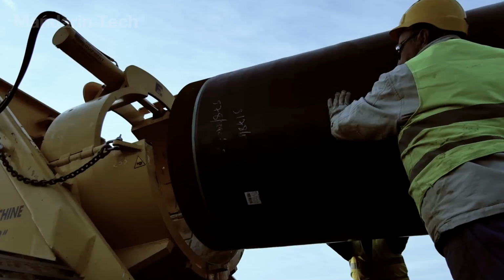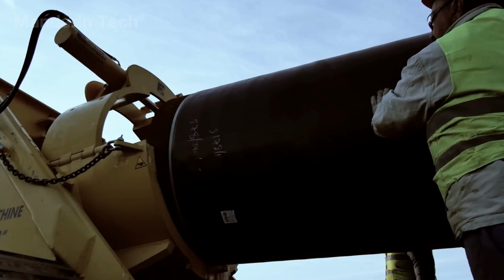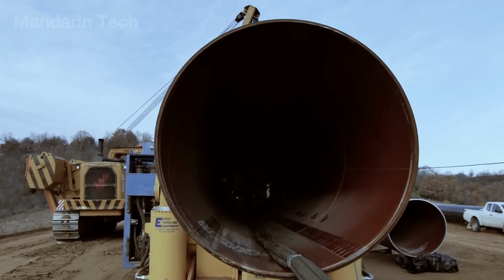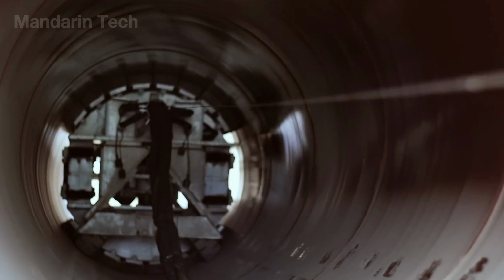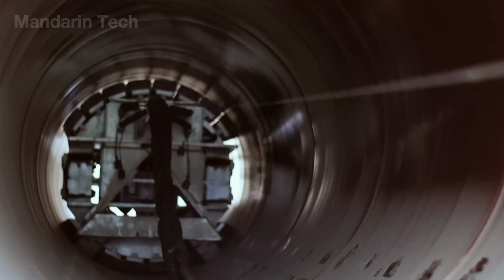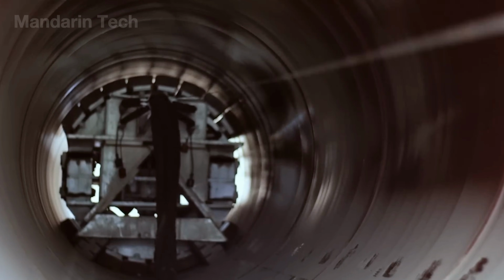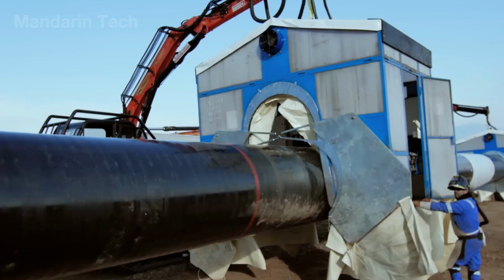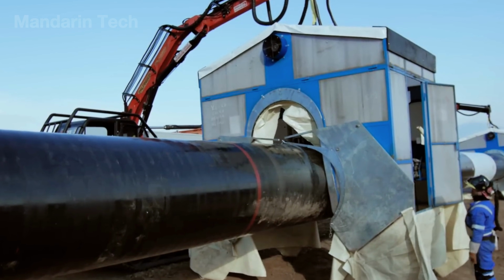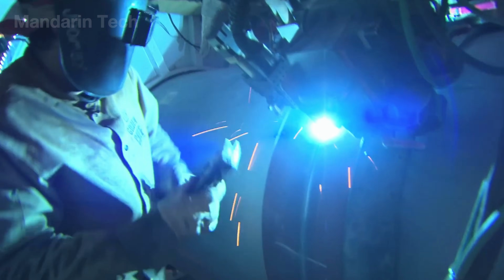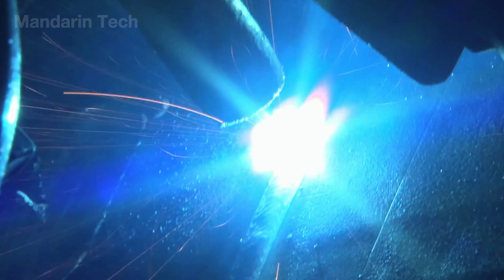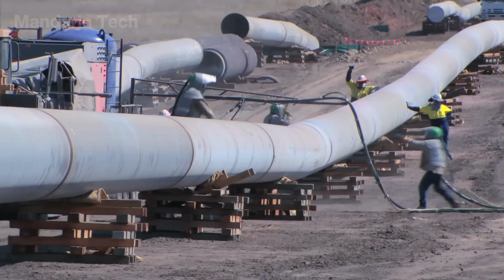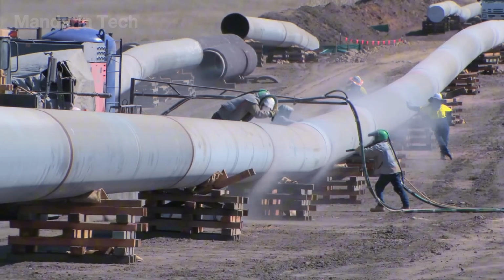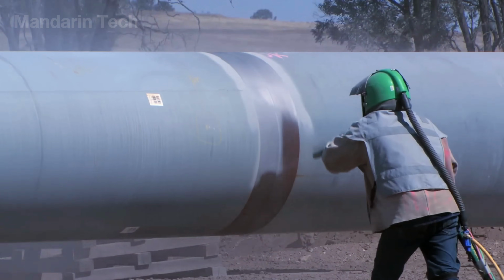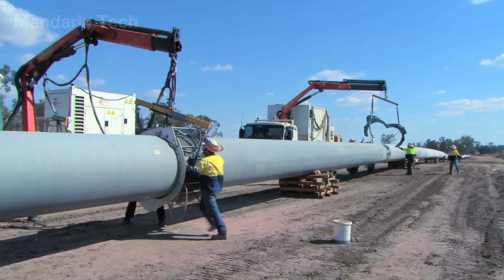At the welding station, a hydraulic internal lineup clamp is inserted inside the pipe joint and expanded using 360-degree gripping shoes, holding both pipe sections perfectly concentric and accurately aligned before and throughout the root pass. An automated welding system, supported by a workforce of around 80 people and dozens of specialized machines, is then deployed and is capable of completing up to 150 welds per day on 42-inch diameter pipes.